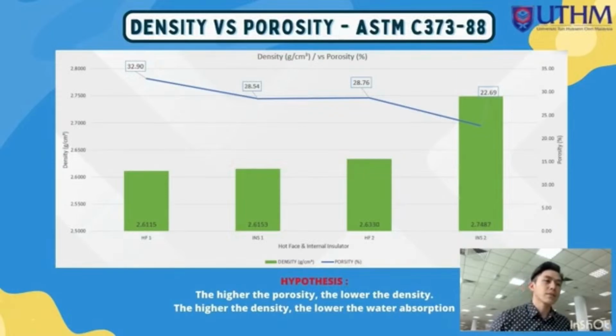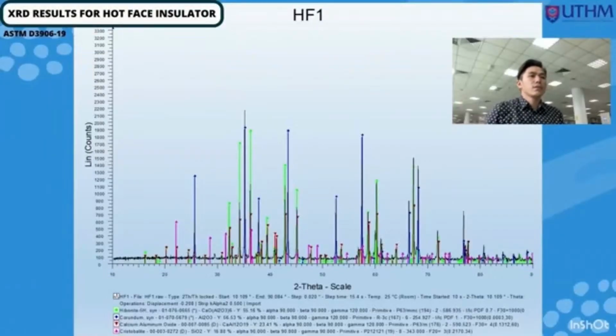As you can see, on the left, the hot face insulator, the first sample, gets the lowest value of density but the highest value of porosity, while the internal insulator, the second sample, gets the highest value of density but the lowest value for porosity. So what is the hypothesis? What we can get from the experiment is the higher the porosity, the lower the density, and the higher the density, the lower the water absorption.